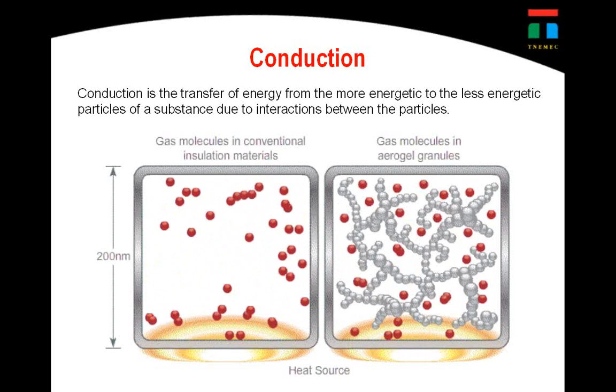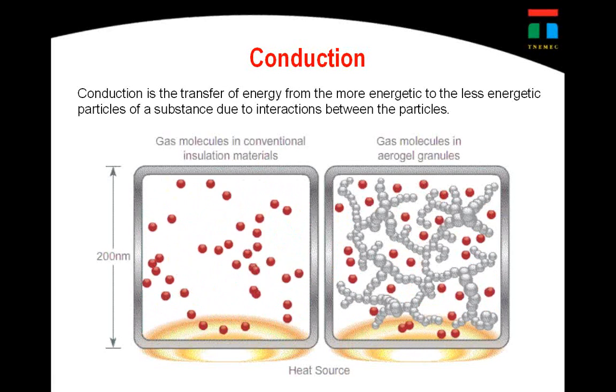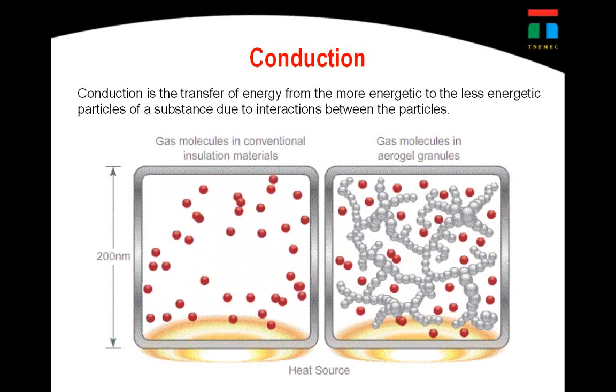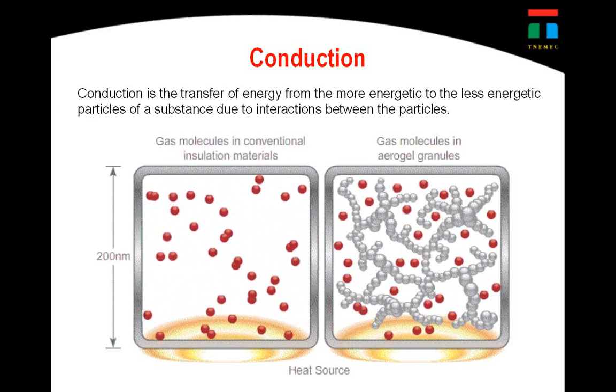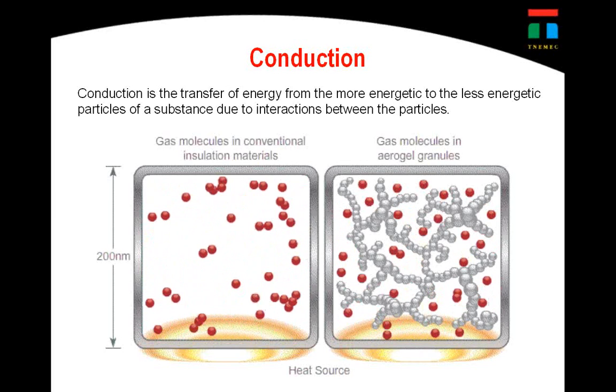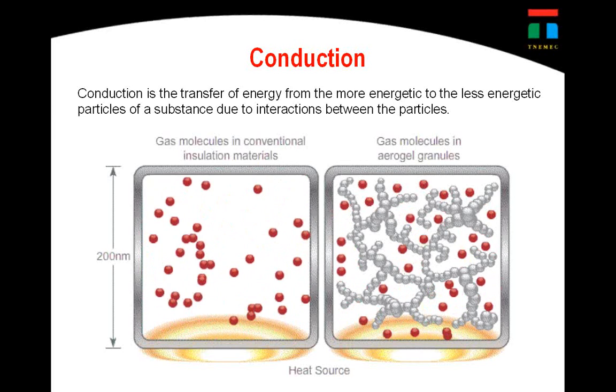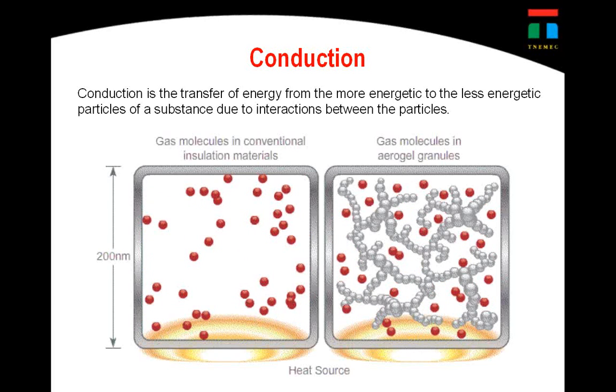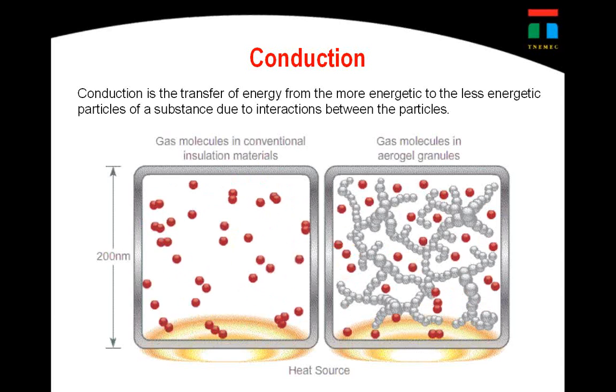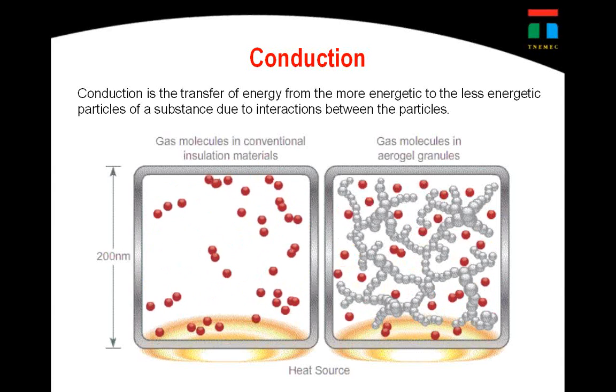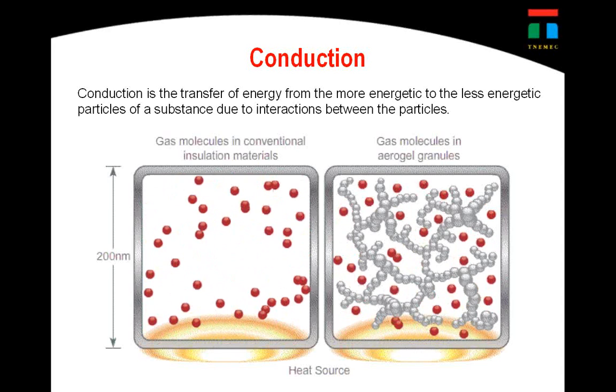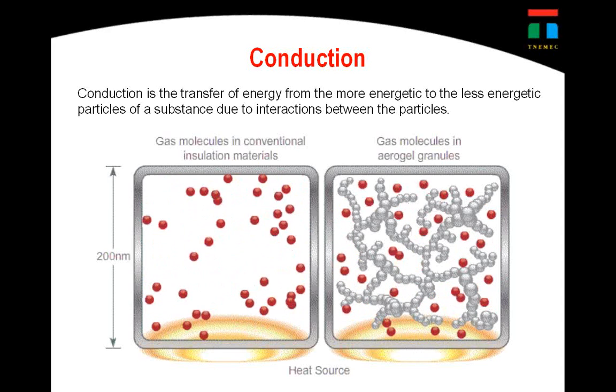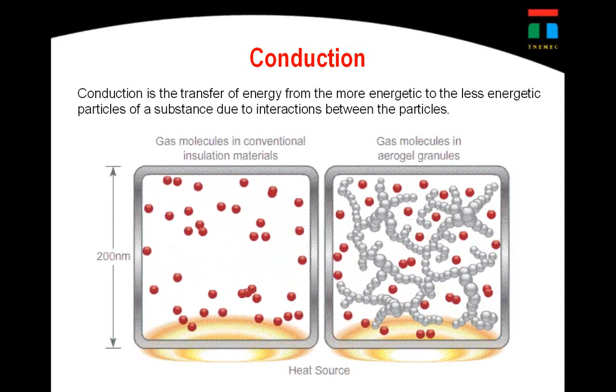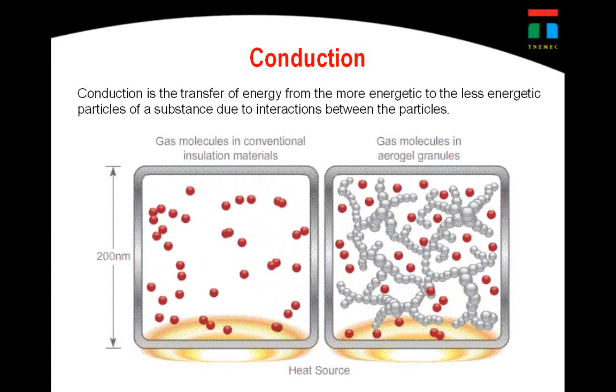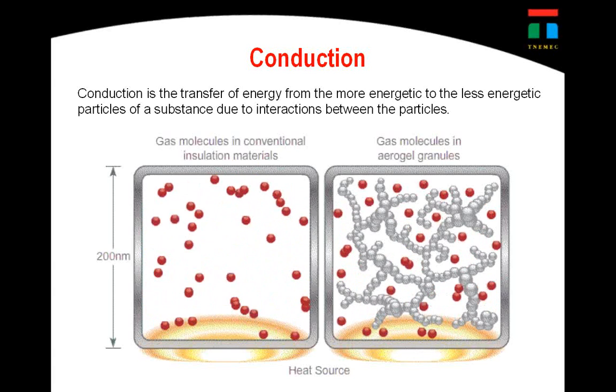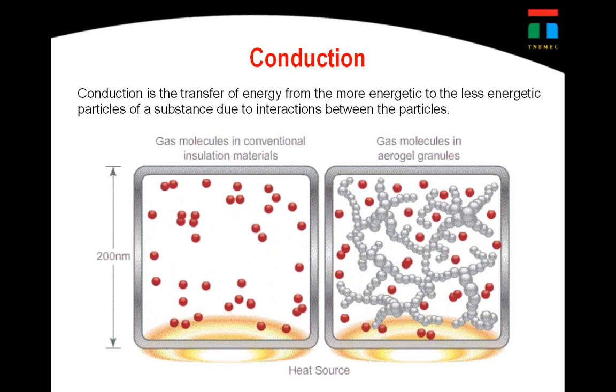If you look at the right side, where you see the aerogel particles with the Aerolon technology, you can see at the very bottom of the slide, the molecules are moving quickly, and as they start going up through these chambers, that's what the amorphous silica aerogel does. It builds these microscopic chambers so that gas or hot or cold molecules of air can't move around fast enough. So imagine, if you will, at the very top of that, you can see they're virtually idle. So this is what we talk about when we talk about the transfer of heat or cold occurring at such a slow rate, because they get caught in these chambers of the amorphous silica and therefore don't translate to hot or cold at the very top of this.